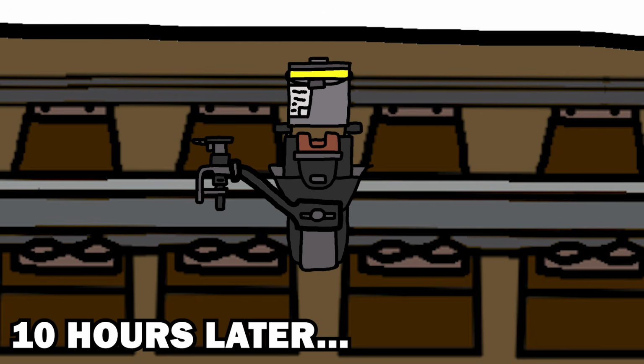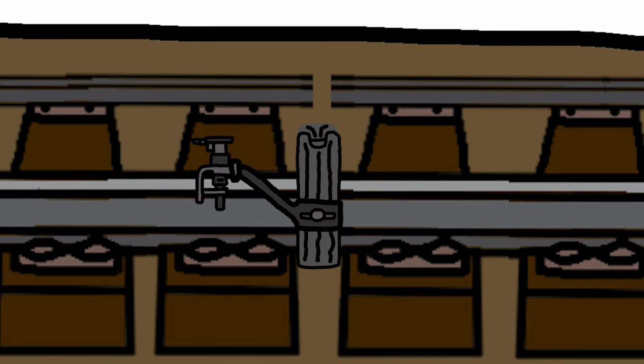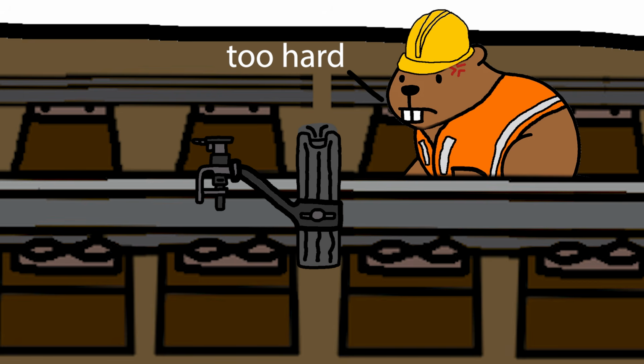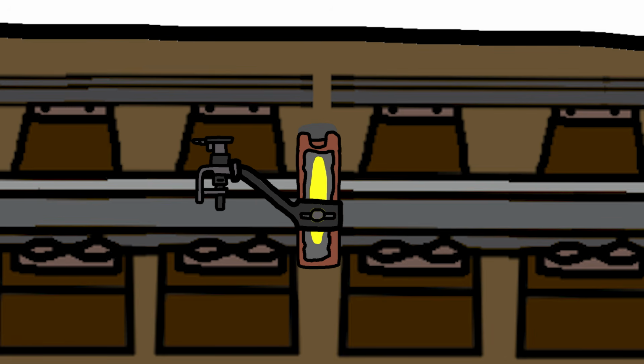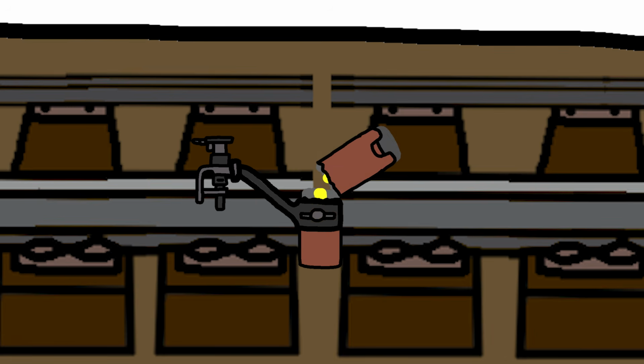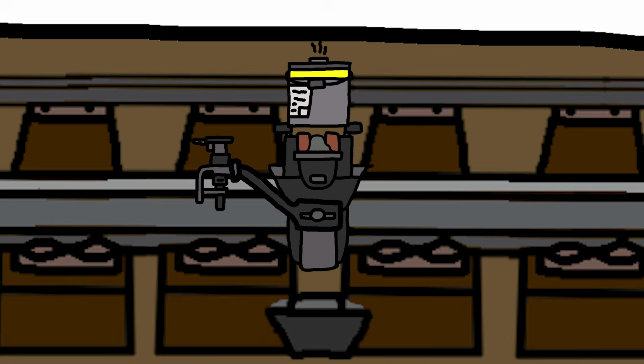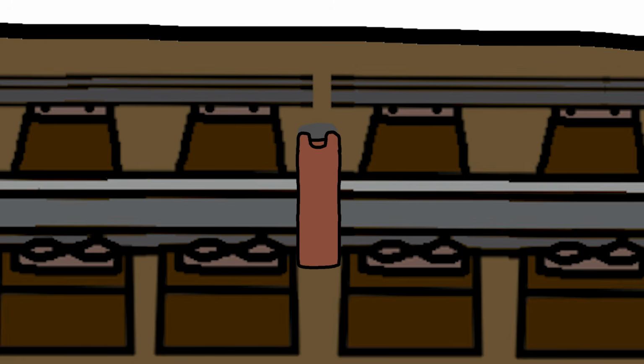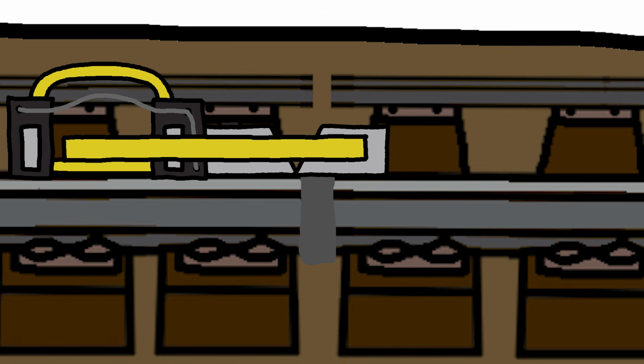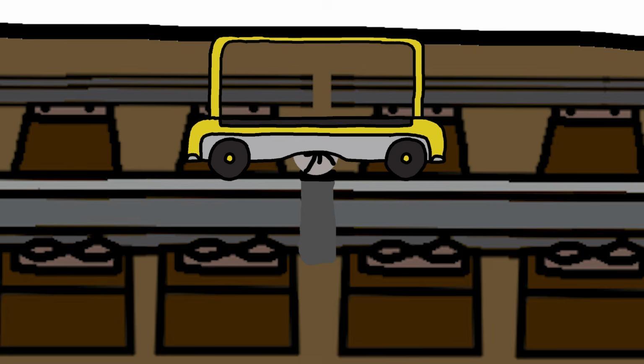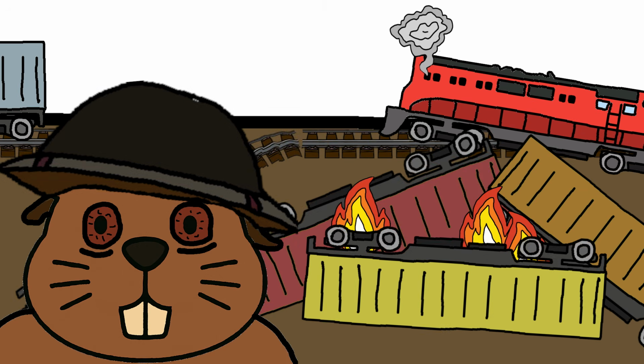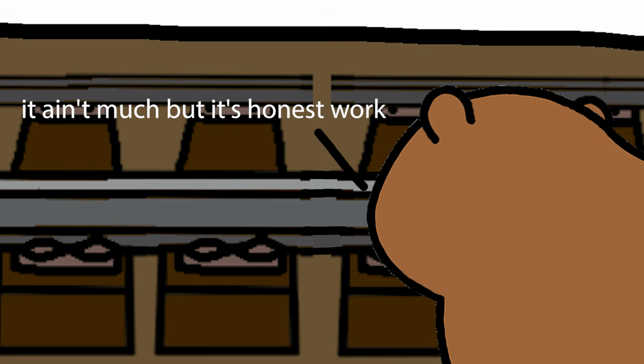If cooled too much, the mold and excess slag will harden and become very difficult to remove. If cooled too little, the metal is soft and can be damaged during cleanup. After the cooling time has passed, the slag pans, mold shoes, and clamping device are removed. The molds are then broken off with a hammer to reveal the weld. The excess weld is then sheared off using a shear press and ground to a flat finish. If too much, derailment. If too little, derailment. With that done, admire it.